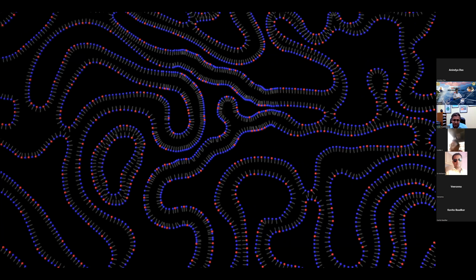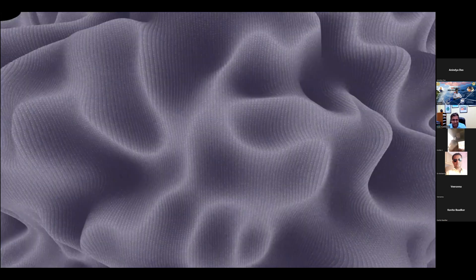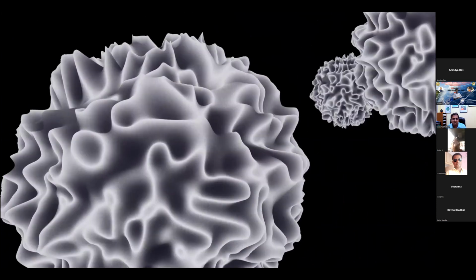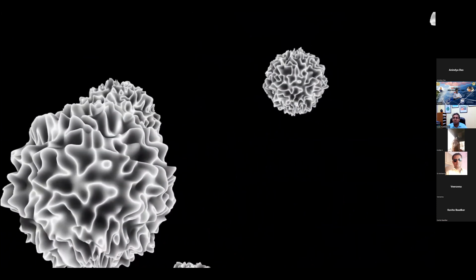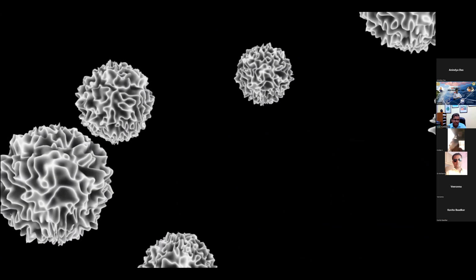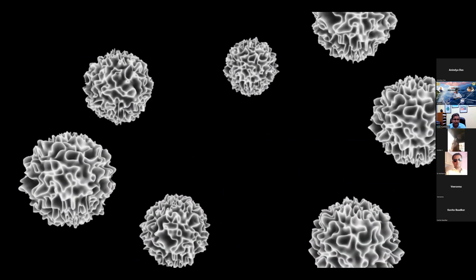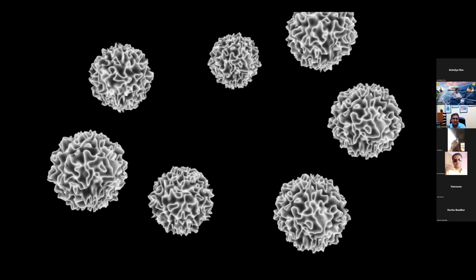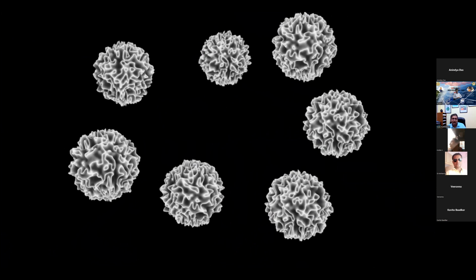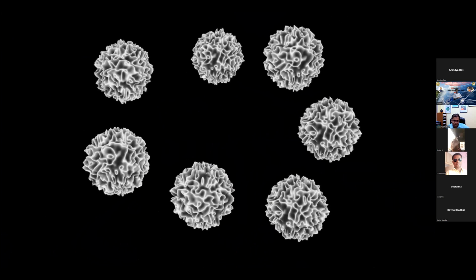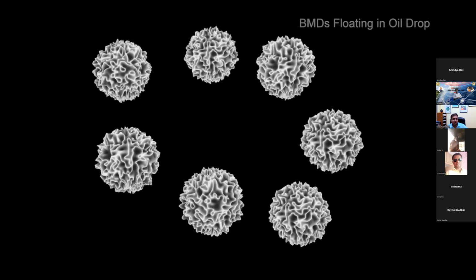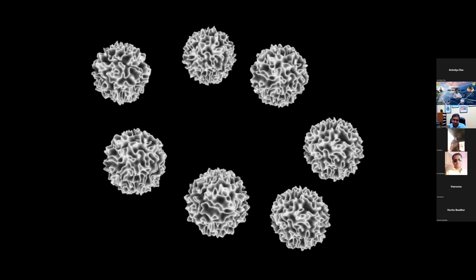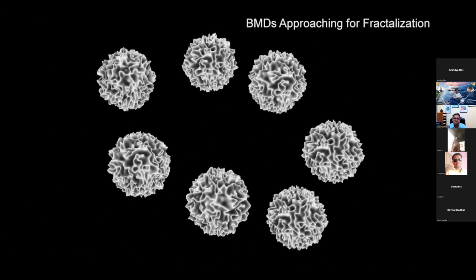What we observe is that these interfaces are not floating flat, but they are in the form of a microemulsion droplet. We call them bicontinuous microemulsion droplets because you have water and xylene continuously trying to mix. So these are the droplets made up of CTAB, water, and xylene, and this is called the template. So there is no silica right now, but the water channel has the silica precursor, which hydrolyzes, polycondenses, and undergoes nucleation and growth to form the silica. The growth is confined into these droplets.